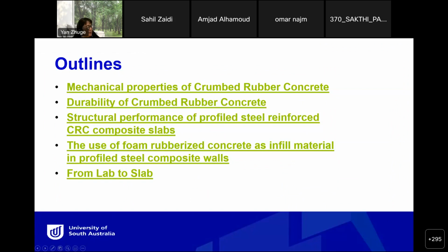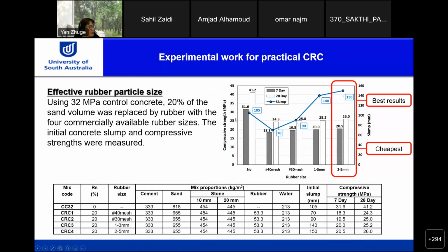So the last thing I want to talk about is from lab to slab. To show some practical research work we have done, we call them from lab to slab. So before we do the real construction, here is a summary of the work for practical crumb rubber concrete. We're using 32 megapascal control concrete, and 20% of the sand volume was replaced by rubber with the four commercially available rubber sizes, because we want to find out the optimal mix design. So the initial concrete slump and concrete strength were all measured. So you see that's the result. That is rubber size. This is the normal concrete, no rubber. That's using 40 mesh, 30 mesh, bigger size, 1 to 3 mm, even bigger size, 2 to 5 mm.